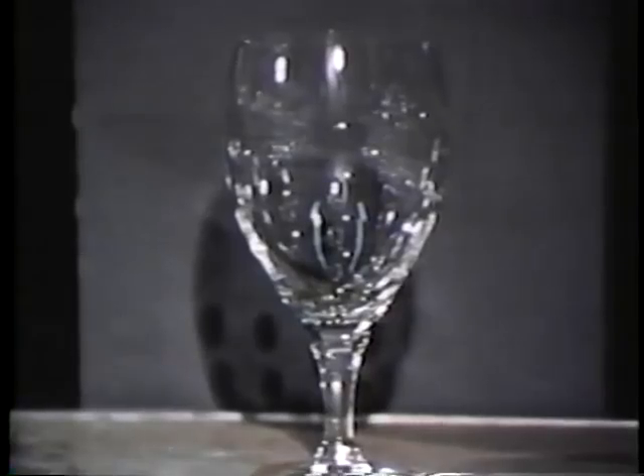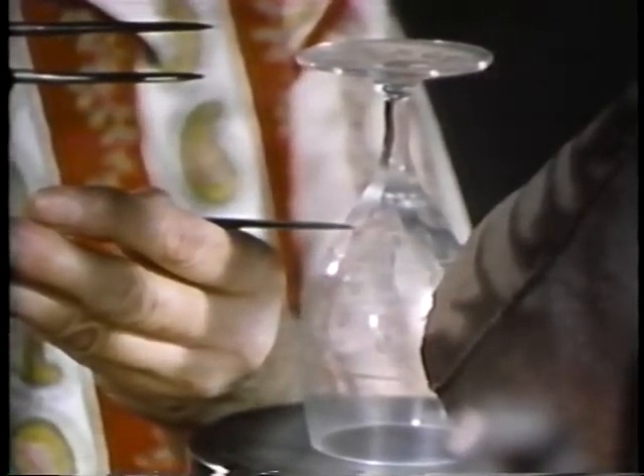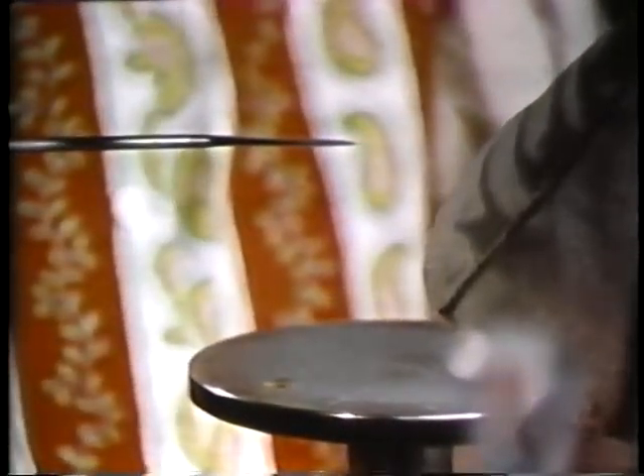We have a sample of every cut pattern — whether goblet, sherbet, wine, cordial, or tea. We bring out the sample and adjust spacing rods which block out the pattern, spacing it out, and we set up the rods using the already-cut sample. Then we mark each piece just for spacing so the cutter knows a certain portion of the pattern goes below the line, above the line, or in between the lines. The marking is done with red lead paint so it won't come off with water — since there's always water on the wheel and on the glass — and we end up with the cut halfway through with guidelines marked off.